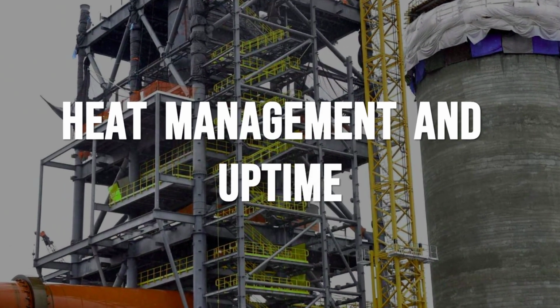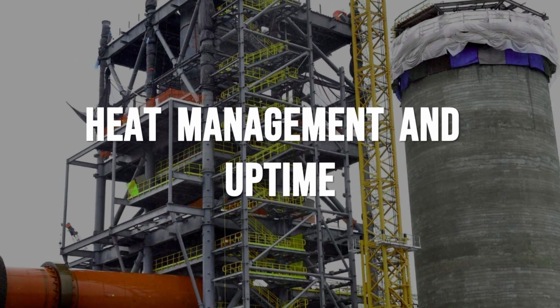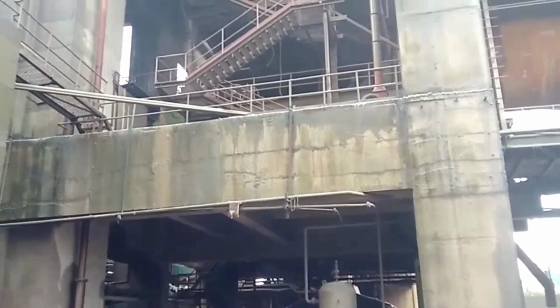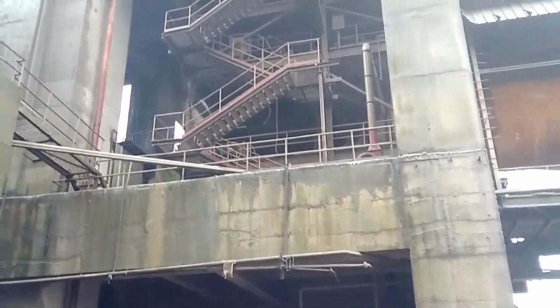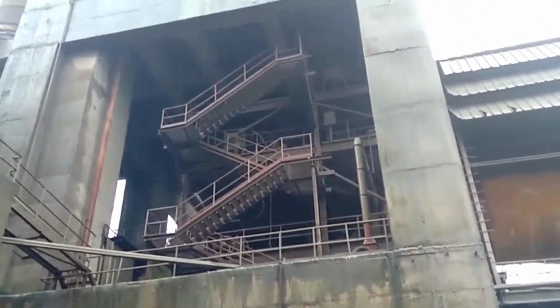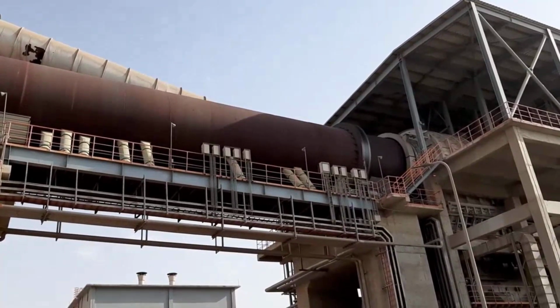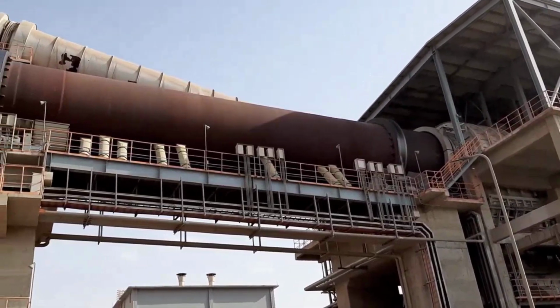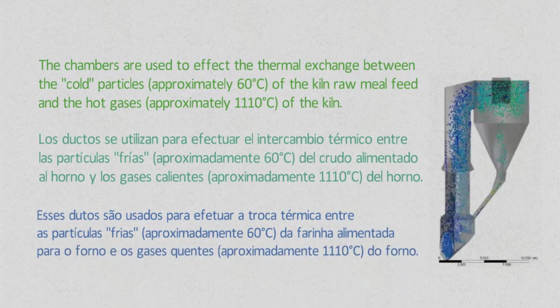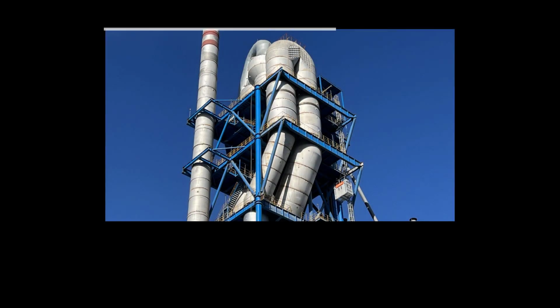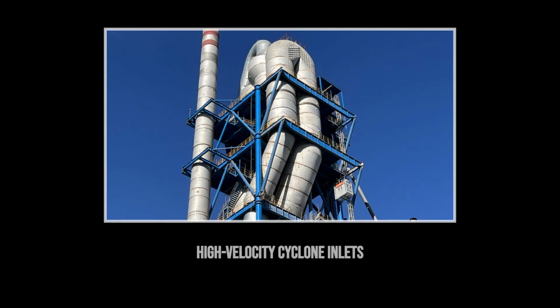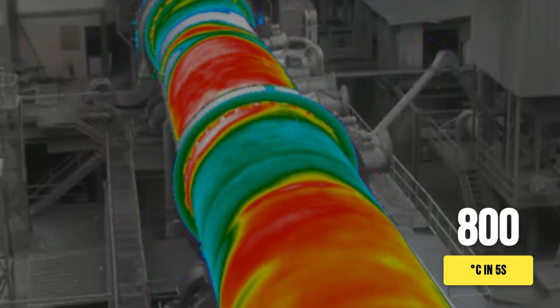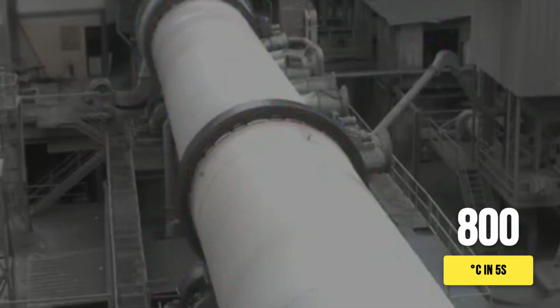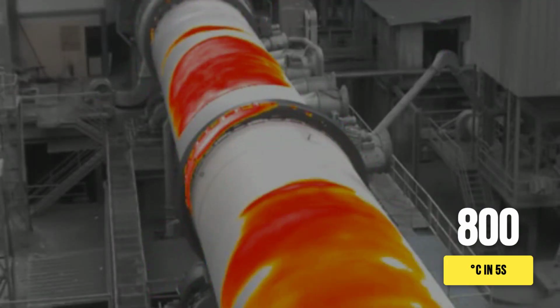Inside Plant A, the preheater tower rises above the main kiln hall, its 6-stage cyclone stack humming with the sound of gas rushing at nearly 40 meters per second. Every second, hot exhaust from the kiln base surges upward, meeting a steady rain of raw meal falling from the top. These cyclones are engineered for speed, each one shaped and sized to maximize contact between hot gas and solid particles, pushing the temperature of the meal from ambient to over 800 degrees Celsius in less than 5 seconds.